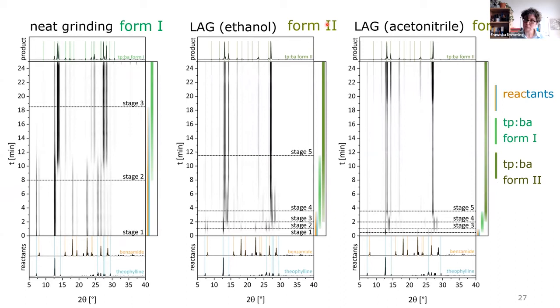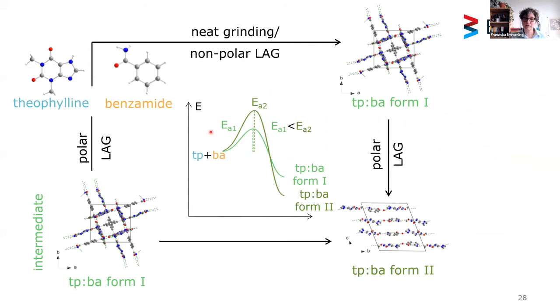We performed further tests, slurry experiments, and so on. And it's clear now that if we use neat grinding and non-polar solvent, we end up with a kinetically controlled product. And in the other case, we see in between the formation of this compound and then end up with a stable, thermodynamically stable form.